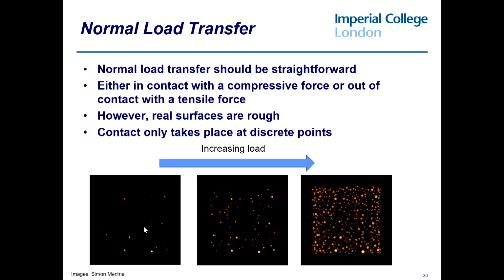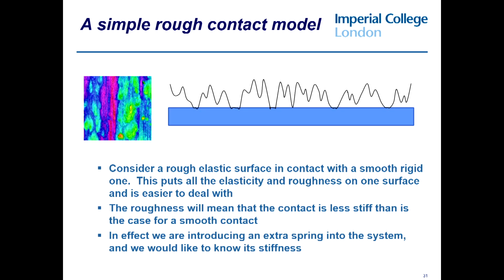Again, we had a collaborative project with Imperial some years ago, and here's some work that Simon Medina did simulating what happens with a contact. Here when it's lightly loaded, there's just a few points in contact, just these high spots. Then as we increase the load, these spots expand, and more points come into contact. And actually, when you put a flat surface down on a flat surface, it comes to look like this. You can model this phenomenon, and you can conclude, not only about the friction, but that a surface is less stiff than it would be if it were smooth.